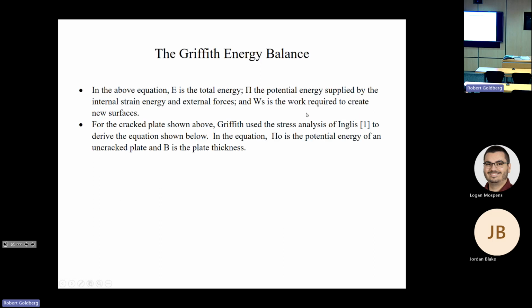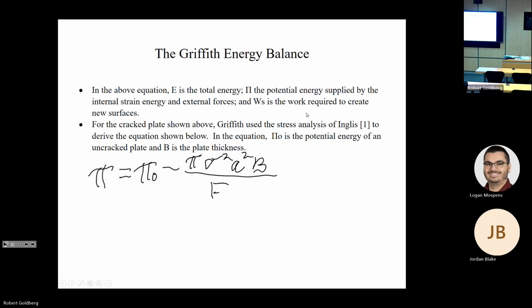Griffith used the stress analysis of Inglis to derive this equation, and we're not going to go through the derivation process, so we'll just say that the potential energy is equal to the potential energy of the uncracked plate minus pi times the square of the applied stress times the square of half of the crack length multiplied by the thickness of the plate divided by the modulus of the material.